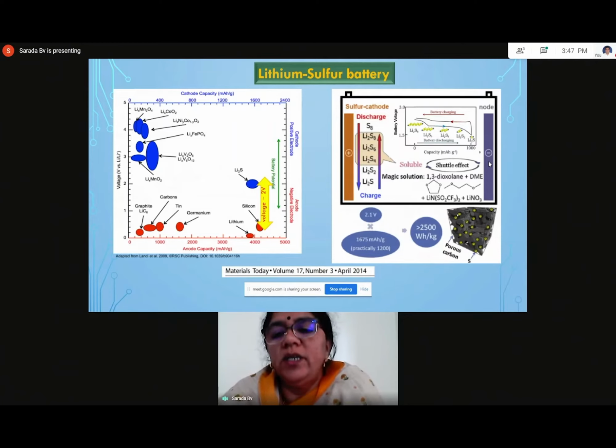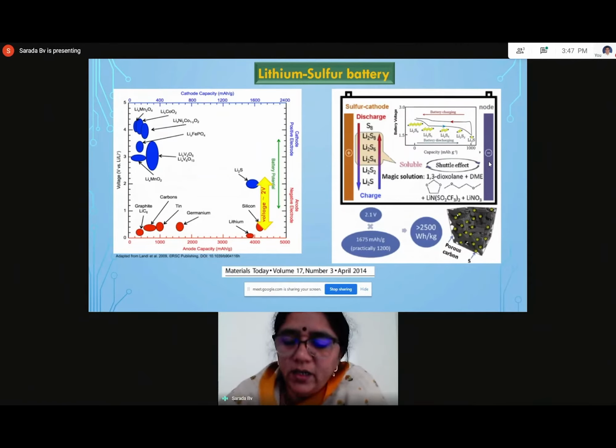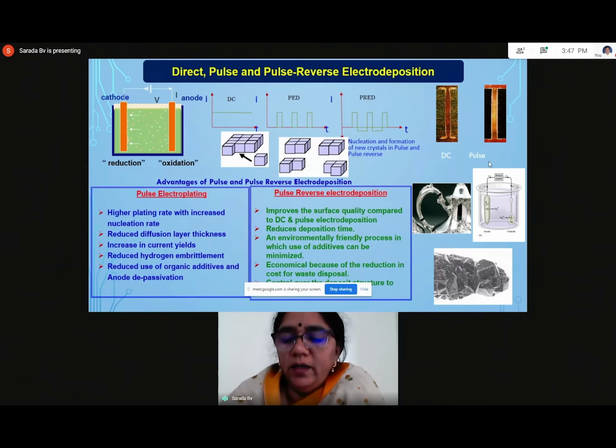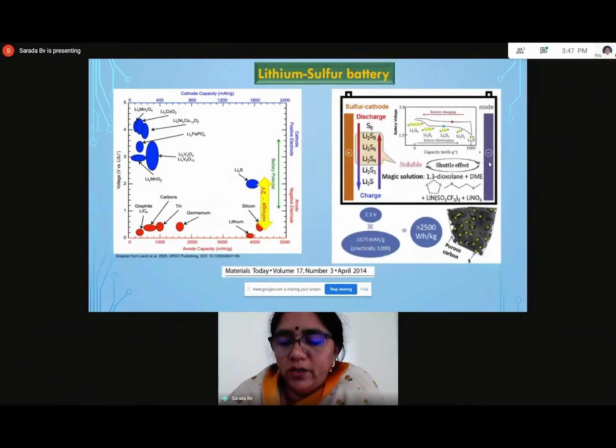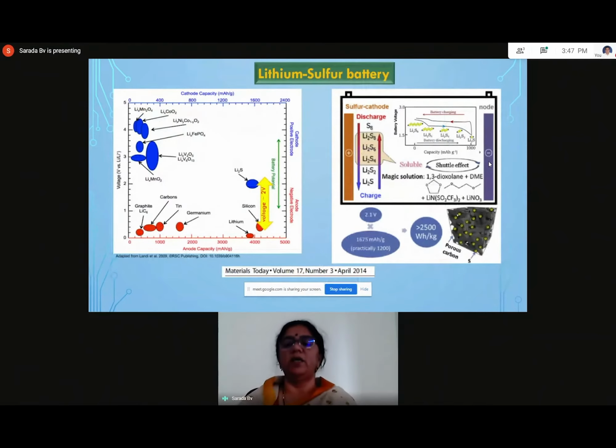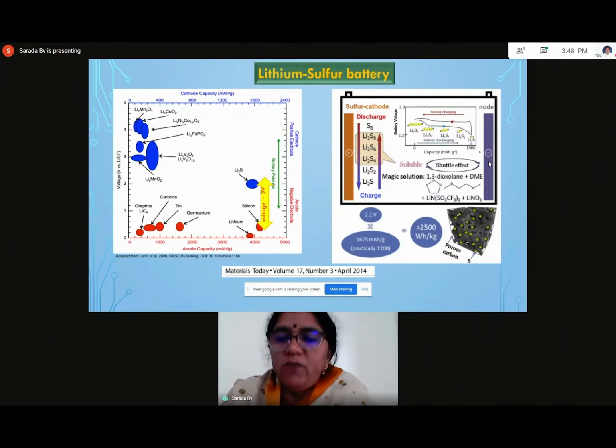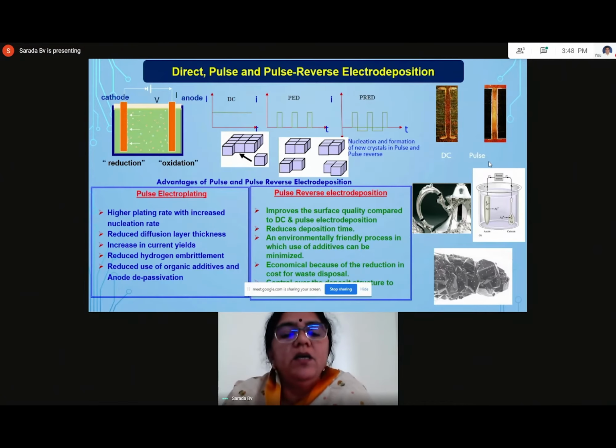So to engineer the cathode part, you have to choose the substrate and also the sulfur nanoparticles in such a way that you can bring out the best performance. And for that, we have used electrodeposition methods. Of course, several methods are used. However, people are finding that these methods give the best performance in the first few cycles, but it fades with each cycle. So in order to improve the performance, we have to come to a particular process.